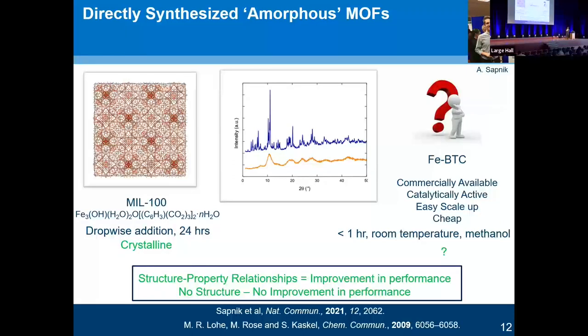Everyone's thinking, yep, that looks great. However, it does have an amorphous equivalent, FeBTC, which Stefan Kaskel published on in 2009. This amorphous equivalent is commercially available. It's catalytically active. It's cheap. It's easy to scale up. And you can form it at room temperature in under 1 hour. But for some reason, we're just not interested in the structure. Why is that? It doesn't seem to me to be an actual reason for this distinction. Crystalline, great, wonderful. Amorphous, very functional, cheap, not wonderful.